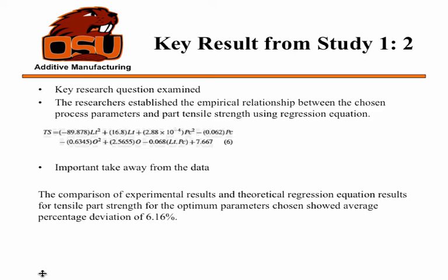So it was okay. They do about 30 to 40 experimental runs to see how the tensile strength obtained from their regression model and the actual tensile strength tested vary, and they have just around 6% deviation from the average value obtained from experiment and the regression model.